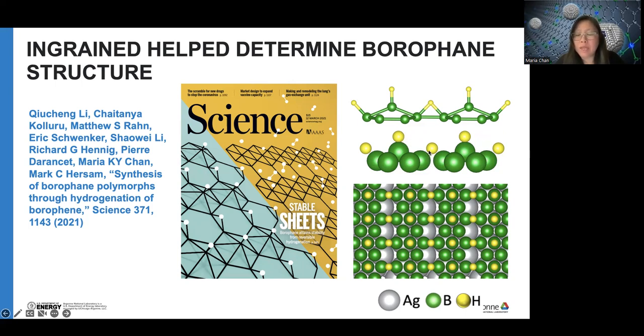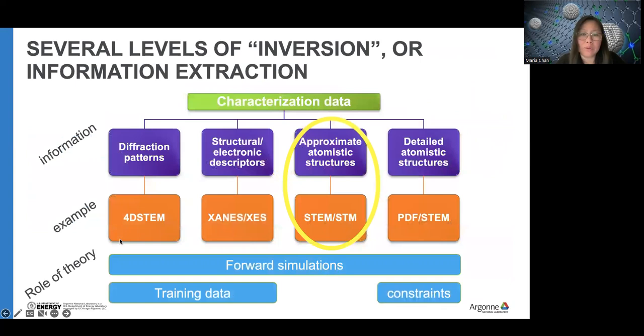So with Ingrain, together with a lot of DFT simulations, we also simulate things like vibrational spectroscopy to validate this structure. We find that the hydrogen sit on 2 different sites, and boron is both cationic and anionic in different parts of borophane. So that was really interesting and different, and that was on the cover of Science a couple of years ago.